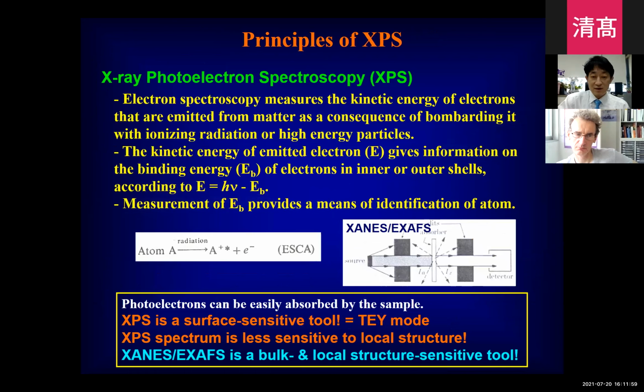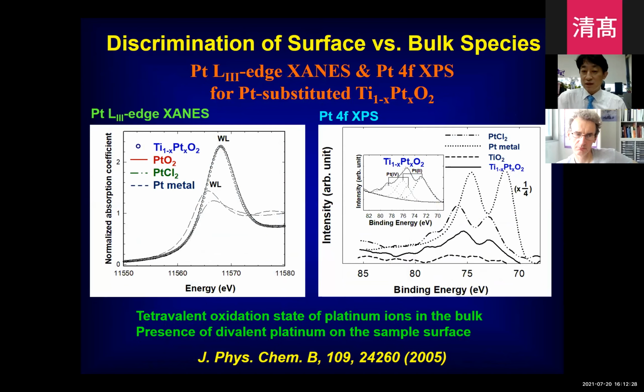Like the total electron yield mode, by using XPS, we can get the information about the surface bonding nature because with this spectroscopy, we measure the kinetic energy of the photoelectron. So if you combine the XPS and XAS in fluorescence mode or transmission mode, we can get separate information of the bulk and the surface. Let me show you one example of the strong point of the combination of both XAS and XPS.